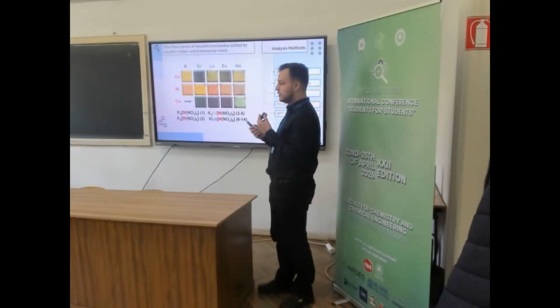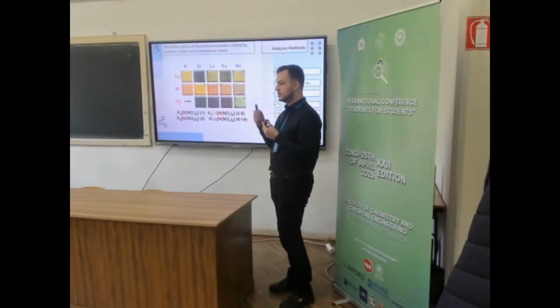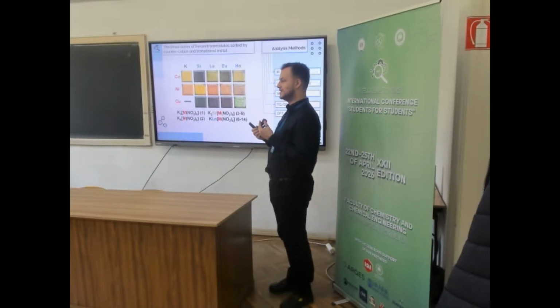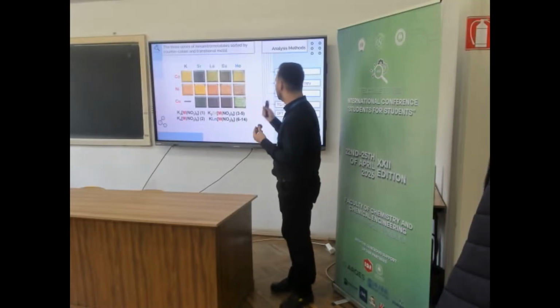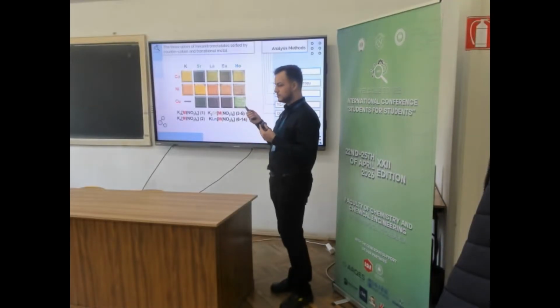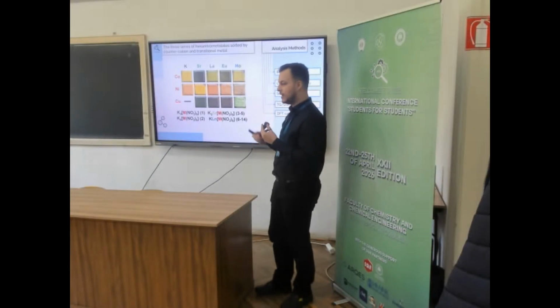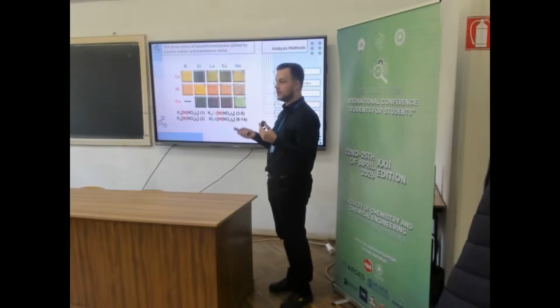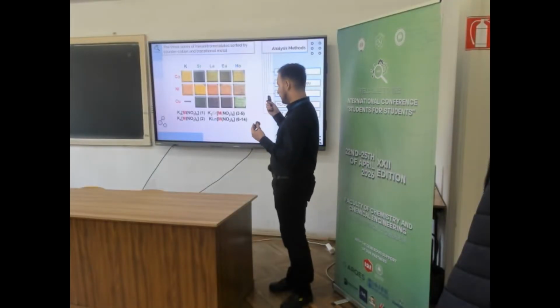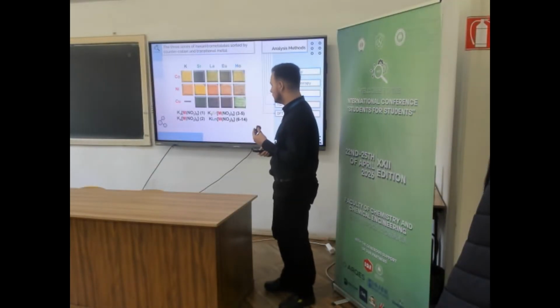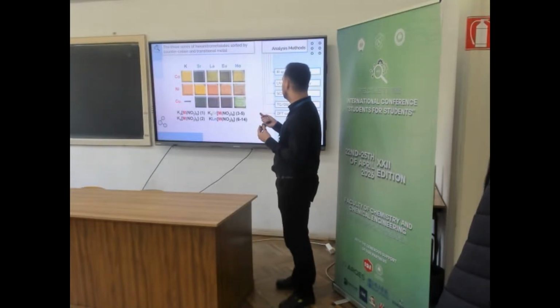And strontium gives off stability through its charge of +2, which increases the polarization of the bond and makes the bond stronger. The volume of strontium also helps because it decreases the distance between ions, and the result is a very stable, compacted structure that doesn't allow water in and makes it very hard to dissolve these compounds.